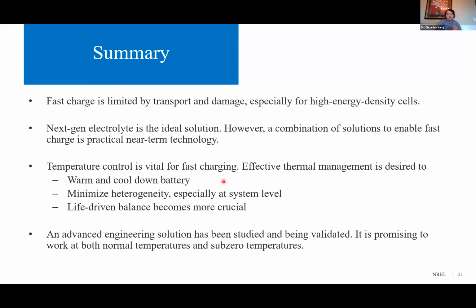Among these strategies, we evaluate that temperature control is very important for fast charging as a near-term technology. An effective method should warm up and cool down the battery efficiently. At the system level, minimizing temperature heterogeneity is vital. Life-driven balance may become necessary. Recently, we worked with Allcell to develop a thermal management solution based on the phase change composite. It's promising that this technology works for both normal temperature and sub-zero temperatures.